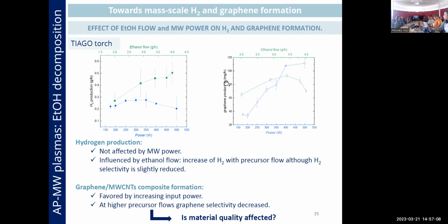What about graphene production? Let's have a look at what is happening with our graphene amount when we increase the power. This is in blue points. You can see that, having the same amount of the precursor, increasing the input power increases considerably the amount of graphene formed. What happens if we increase ethanol flow, keeping the power constant? Okay, it seems to increase with ethanol flow and then decrease. Why? Because under these conditions, we are forming a larger quantity of light hydrocarbons, such as methane or ethylene.